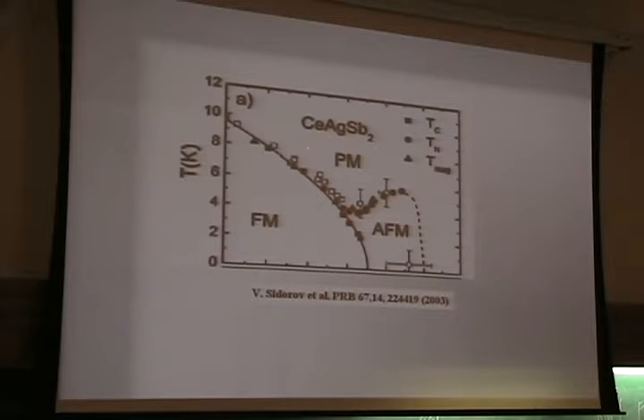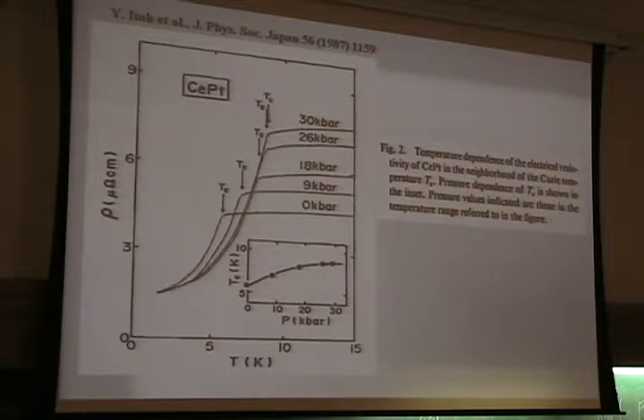There is another system, cerium silver antimony. This system also seems to go to an anti-ferromagnetic phase before it reaches the quantum critical point. So there are a few more examples, but all of them seem to change the kind of ordering before they reach the critical point. What we intended to do in this work was to collaborate on one more ferromagnetic system and try to build the phase diagram, and see if this system could go to a quantum critical point without changing the kind of magnetic order.